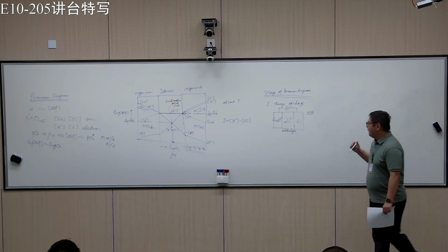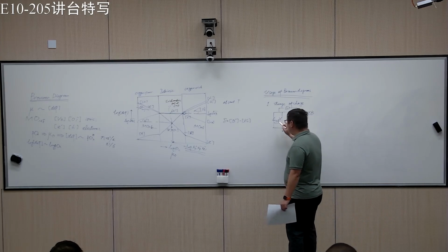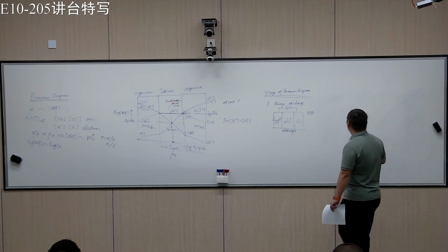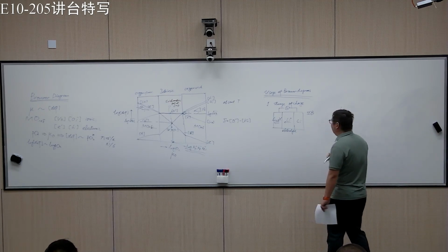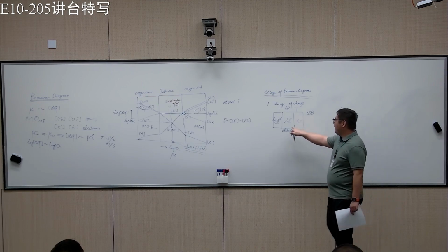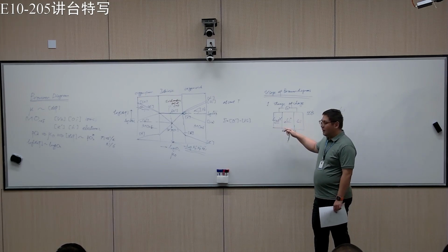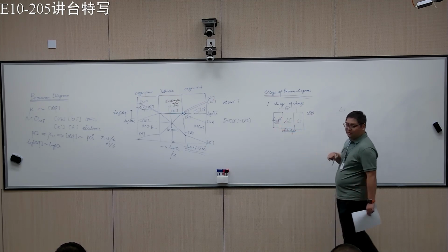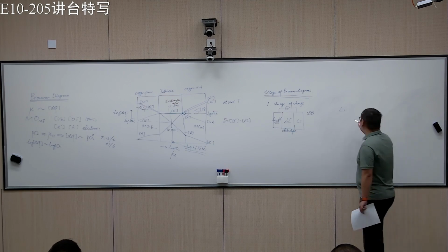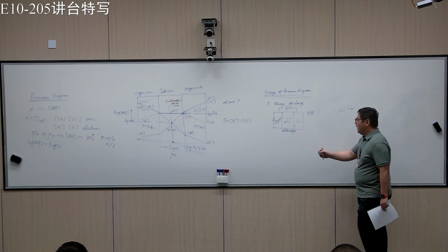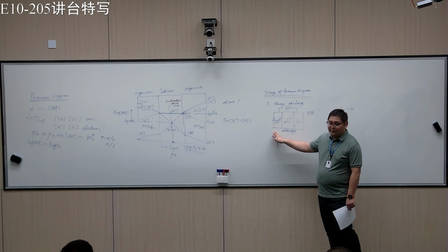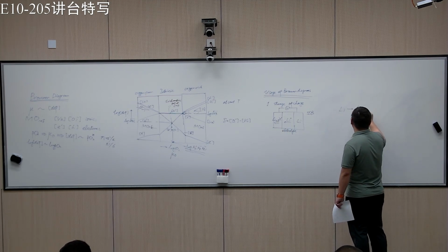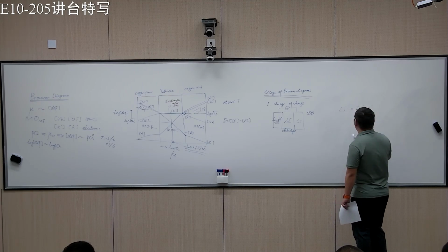The way to do that is by changing the non-stoichiometry. So you can write an equation. For example, if I put more lithium into the structure from the anode, because it's lithium metal, to the cathode, then using the language of defect chemistry it will be something like lithium interstitial and also electrons.